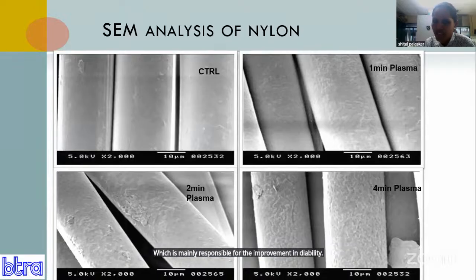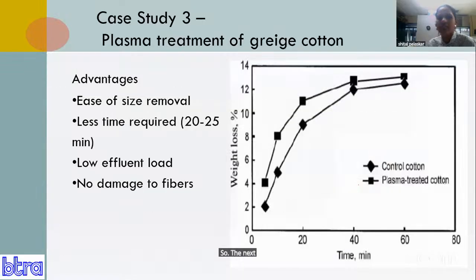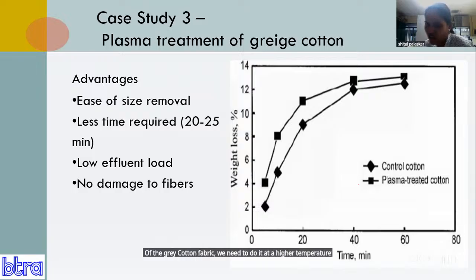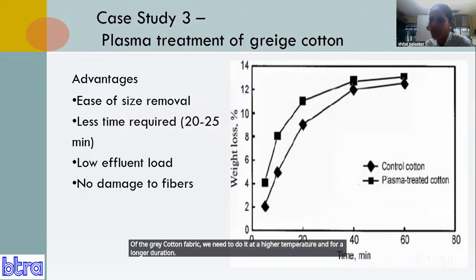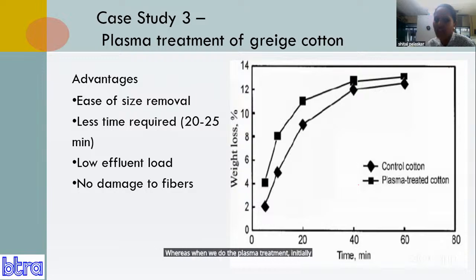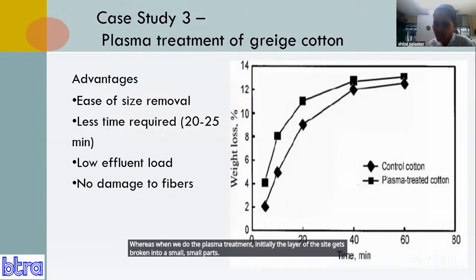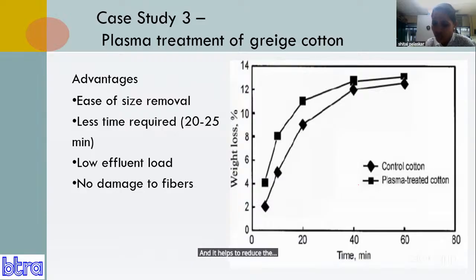of the material. The next is the desizing of the gray cotton fabric. When we do the desizing of the gray cotton fabric, we need to do it at a higher temperature and for a longer duration. Whereas when we do the plasma treatment, initially the layer of the size gets broken into small parts, and it helps to remove the size very easily.